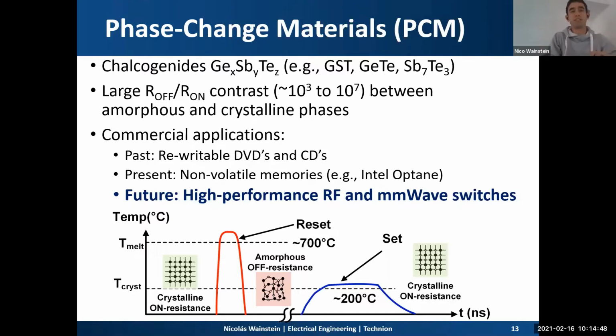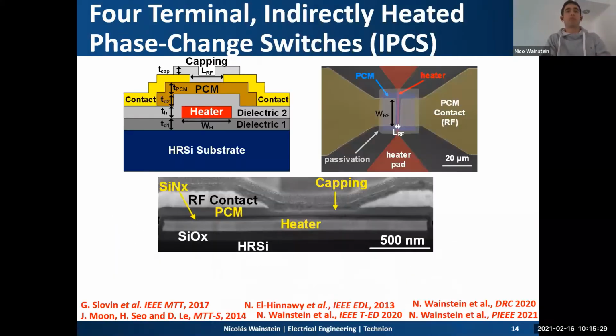The phase transition in these materials is thermally activated. Suppose that initially the PCM is in its crystalline phase or low resistive state. To amorphize the PCM, a large amplitude current or voltage pulse is applied so that the temperature will rise beyond the melting temperature, and the fast quenching or cooling process will freeze the atoms in a disordered amorphous manner. Conversely, a mild amplitude pulse will anneal and crystallize the PCM back to its crystalline phase. Hence, the process is reversible. The 4-terminal indirectly heated phase change switch, IPCS, has been proposed for high-performance RF applications thanks to its state-of-the-art cutoff frequency.